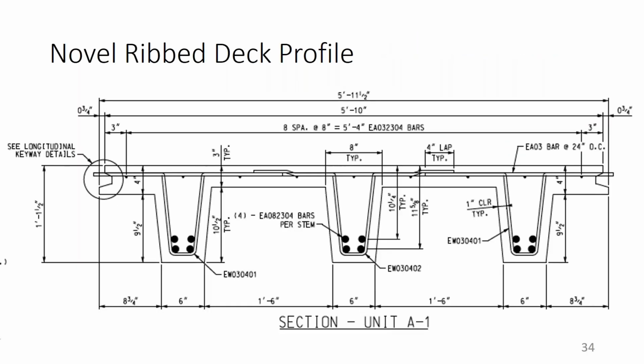This is the cross-section design, showing again the 3-inch typical depth of the panels in the middle. And again, for experienced designers, this may be a little odd, such heavy reinforcement at the bottom for such a thin deck. That is true, but it's not a concern because the UHPC is so strong in compression. For service conditions, the compressive stress was about 7 to 8 KSI, and that is nothing for the UHPC that was used. The reinforcement on the bottom, by the way, is 4 number 8 bars.